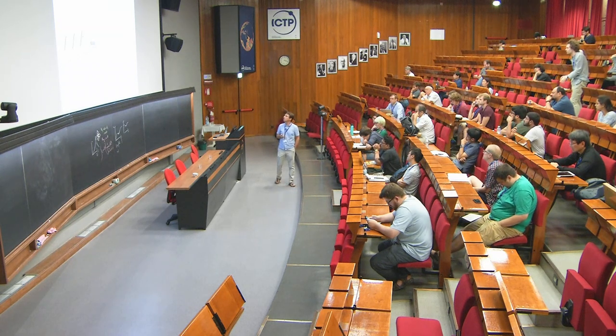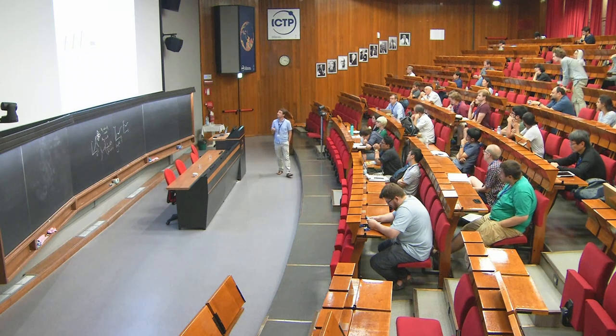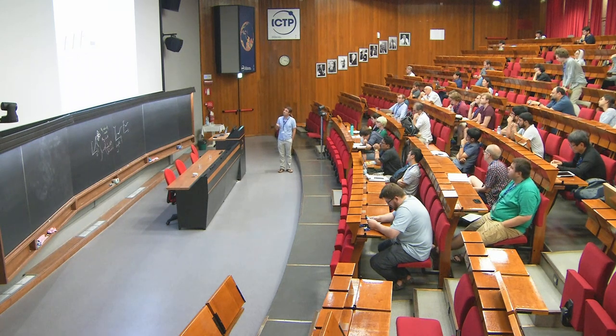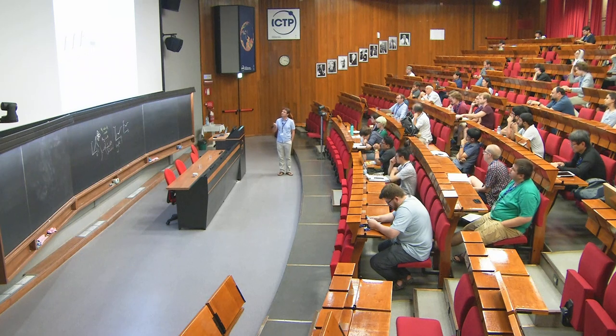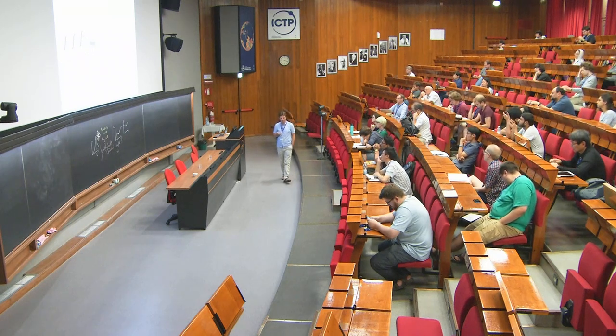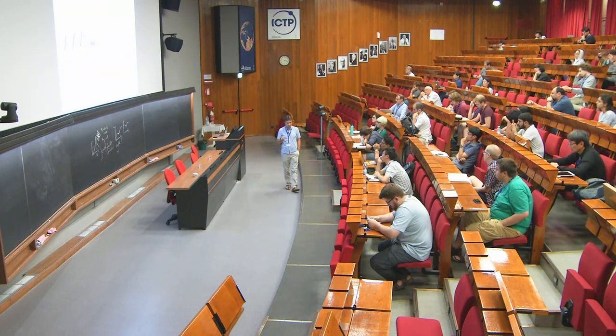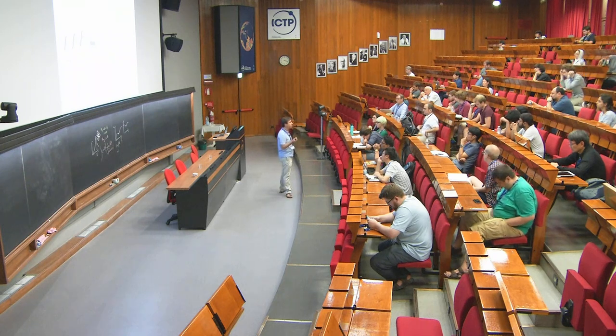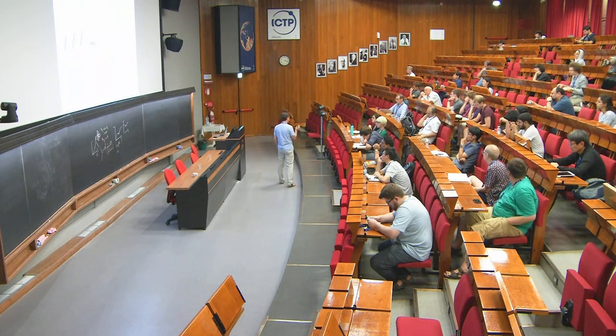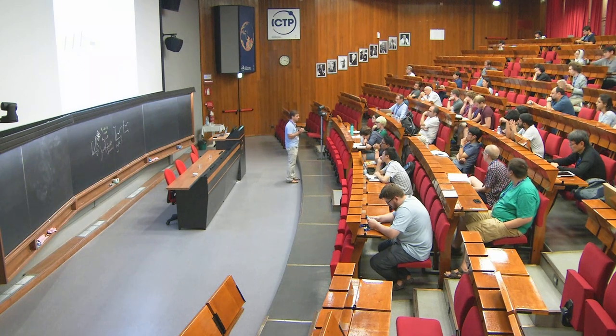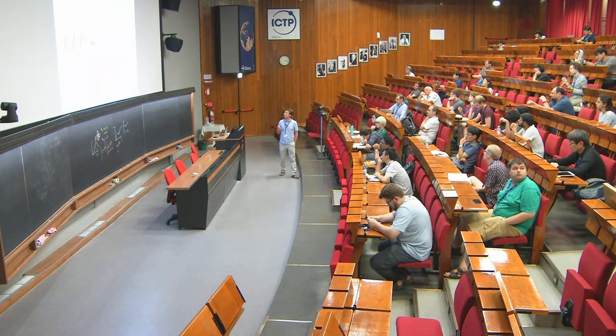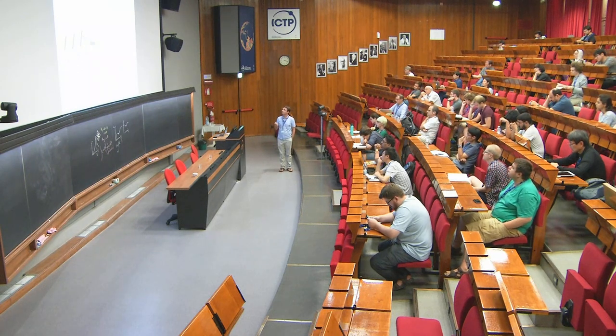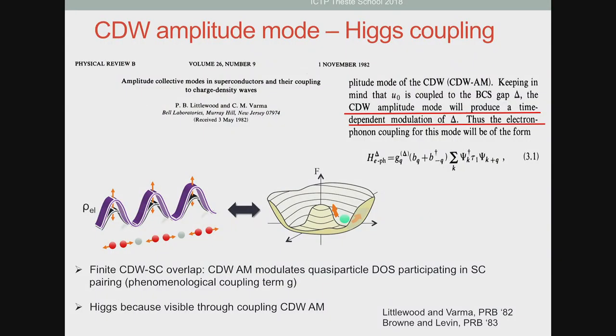No. So there is a related effect. There are some constraints to this coupling. First, you need to have a coupling that is strong enough, and this is usually achieved when the two mode energies are close enough in energy. And then the other thing is you need to have a phonon that strongly modulates your gap. And this was presumed to be the case in this charge density wave superconductor.